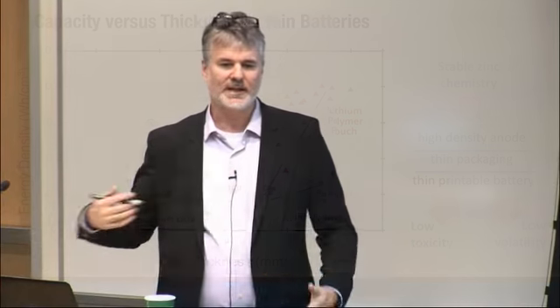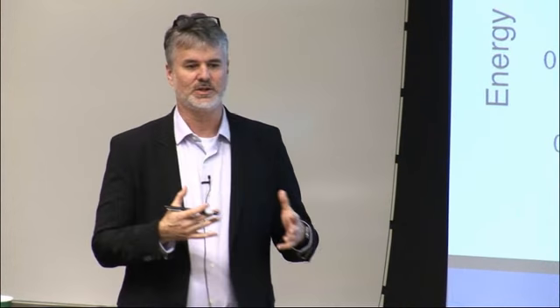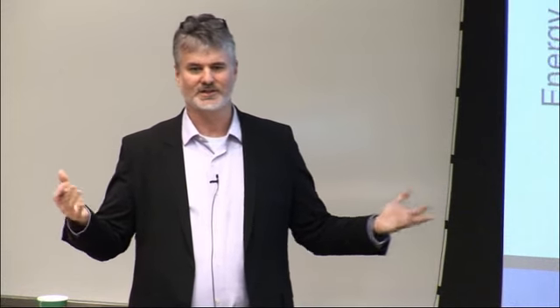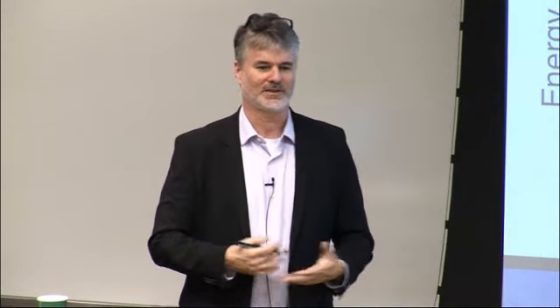And it's largely about the stability. I mean, there's a lot of smart engineering of all these materials, but it's largely about that packaging constraint. Because we're using printable, air-safe materials, we don't need 200 microns of packaging on either side. We need 50 microns of packaging because it's already air-stable. It's not that moisture sensitive. And so overall, we can get in the same very thin device a lot more active material per unit thickness of device, so we can get a lot more energy.